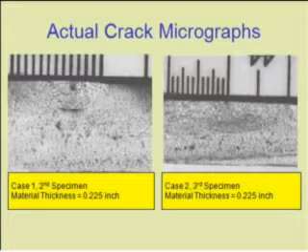EDM slot in fatigue mode, and machining off the EDM slot. So we had a tightly closed crack in an as-machined panel. And that was what we presented for the first inspection go-round. Now, by changing the shape of the EDM starter, we can change the shape of the crack that is grown. And by changing the mode of crack growth from bending to bending and tension, we can control the shape of the crack.